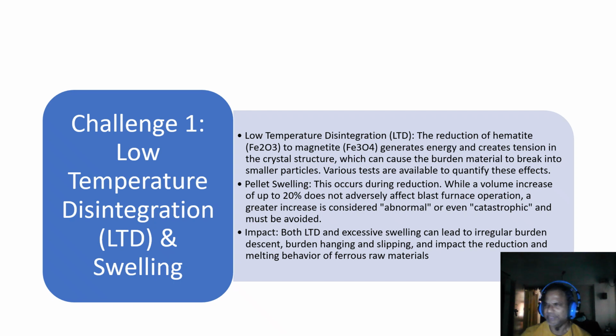Now coming to our next slide about challenge 1, which shows the low temperature disintegration and swelling as one of the big causes. One of the primary challenges with raw material quality is related to their behavior during reduction, that is known to all of us. The first, low temperature disintegration, LTD, occurs when hematite is reduced to magnetite, generating energy and creating internal tension in the crystal structure. This tension can cause the burden material to break down into smaller pieces or particles.